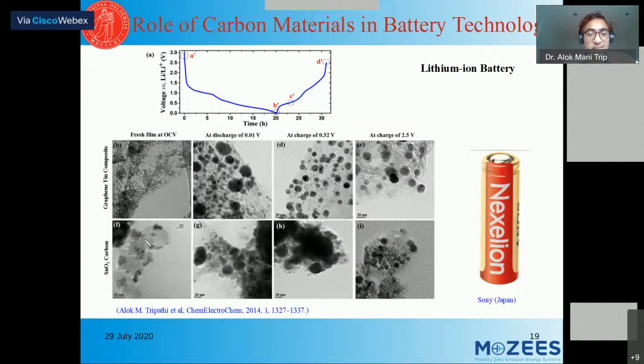So we can clearly see in the post-mortem analysis, dismantling the cell under the transmission electron microscope, that if we have a two-dimensional carbon, it supports the particles very well and gives you very nice performance. And this increases the life cycle of the cell. This Nexelion battery, which is used in Sony cameras for low temperature operations, uses this kind of carbon-based material with different composites. In my research, I saw that if you replace the carbon and use graphene, it could give a much better result.